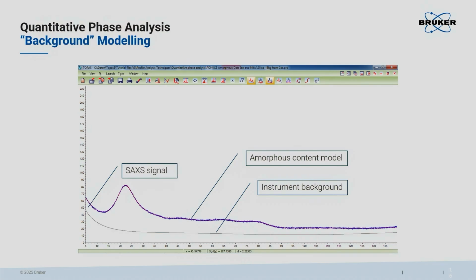The same thing for the instrument background. So I can also determine the instrument background with a sufficient standard. And if your instrument does not change, you can use this as a model for all your subsequent analysis. You will not use it as a hard constraint. You will typically add a linear background function on top of that and refine on these parameters a little bit. This allows you also to distort these models a little bit, but it can be done. It is a little bit more laborious, but if you're doing a type of analysis where the background is of importance because it has important data, then I think you will find this useful.